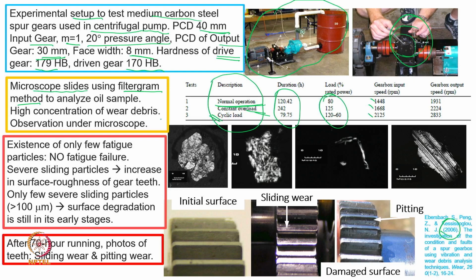Now, they found a very high concentration of wear debris, which indicated that when they accelerate the load condition and the speed condition, they find a lot of particles, a high concentration of wear particles. Now, they observed under a microscope, again this is an optical microscope, we have not gone to the SEM. So we are not talking about smaller particles, we are talking about bigger particles. You can see a big particle here, another particle here. However, there are small particles also here, and then there is another big particle. So big particles are there, but small particles are also there.